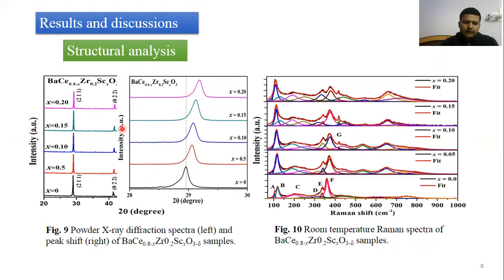The diffraction peaks were found to shift towards a higher 2 theta angle, which is a clear sign of increase in scandium concentration in the samples, and also the decrease of lattice parameters. At the right, figure 10 shows the room temperature Raman spectra of the compositions.